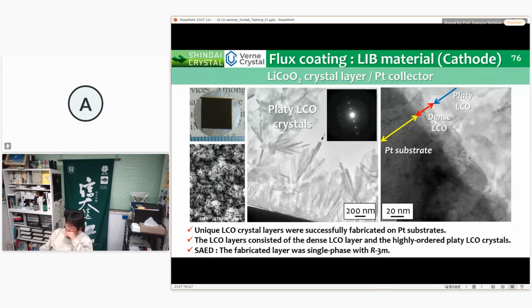The LCO layers consist of the dense LCO layer and the highly-ordered platy LCO crystals. In addition, from the SAED image, the fabricated layer was single phase with R3 bar M structure.